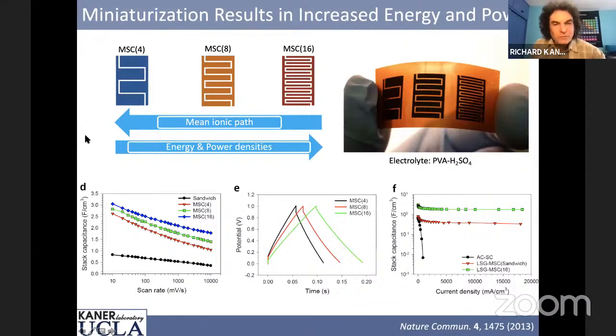And when you do this, what we find is the more interdigitated electrodes, the closer together, the higher the performance. And so here's 4 interdigitated electrodes. This is 8, this is 16, and of course the 16 works better. We just put a drop of polyvinyl alcohol with sulfuric acid on this.